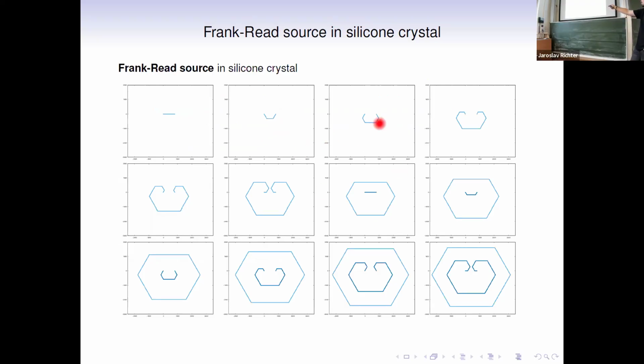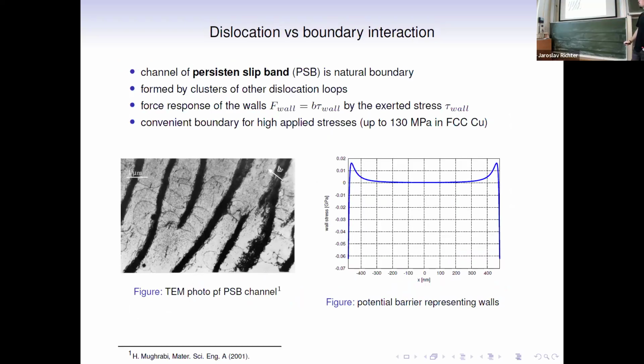Again, the dislocation is bowing out, and you can see almost negligible effects of the curvature. After reaching some minimal critical length, topological changes appear, forming one closed loop which keeps expanding, and a straight line which again keeps bowing until it reaches some total critical length, when the 6-fold crystallographic structure continues.